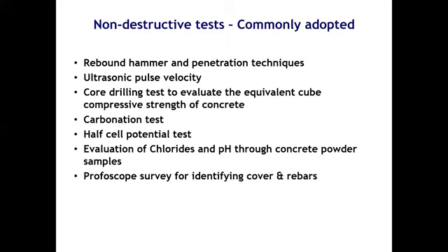As I said earlier, we don't get even GA drawings, so we don't have a structural drawing. When you want to address additional load carrying capacity of the member, obviously you need to go for a Profometer survey so that you get the details of reinforcement which is available approximately. And there are a few other tests like core trepanning for finding out the loss of pre-stress, but very limited knowledge and usage is available at present. As I said, our managing director's SCRC is doing this technique, and they are able to predict the loss of pre-stress in the concrete.